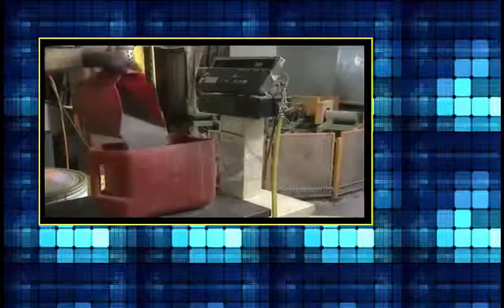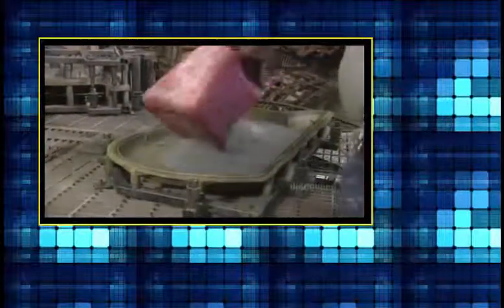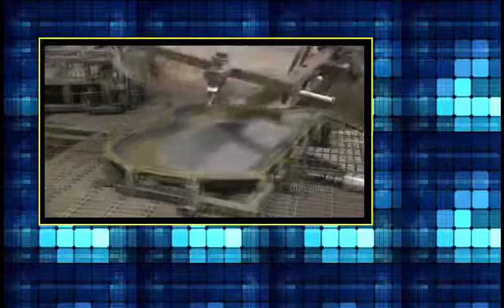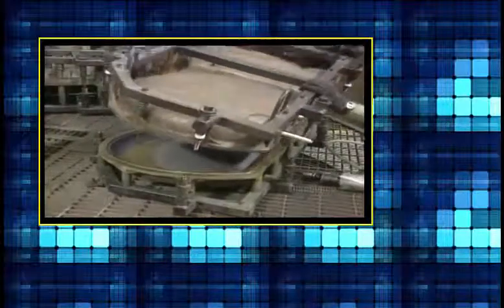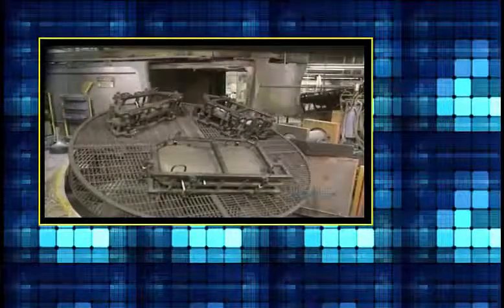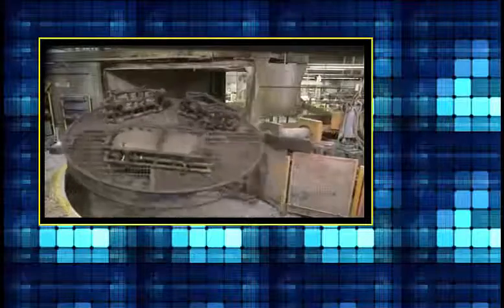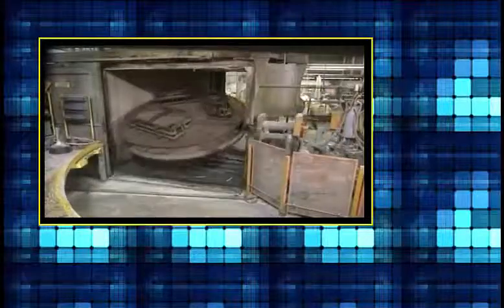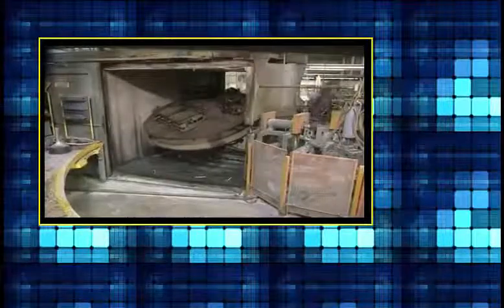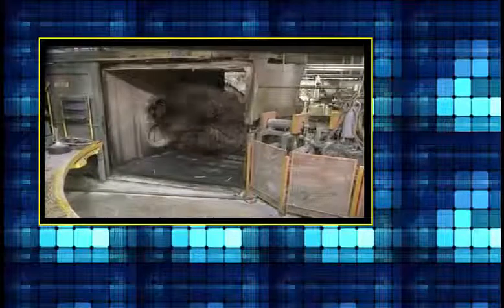This previously colored powder has a 35 mesh size, which is just a little larger than flour. Low-density linear polyethylene is poured into the bottom of the mold. The mold has a cover which will be well closed, then placed on a steel support. This support is articulated by an arm on 2 rotation axes simultaneously. This action allows the plastic powder to distribute itself thoroughly throughout the mold.